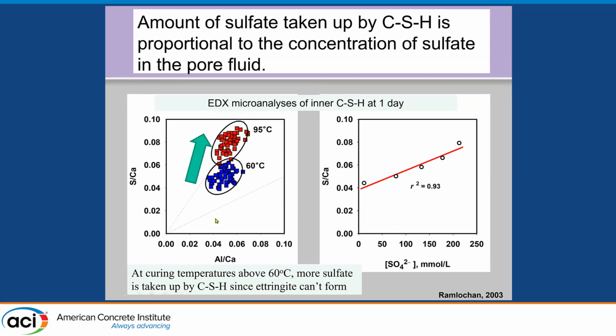And if you look at temperature effects, these ratios of a bunch of EDX points on CSH, what you see here is the sulfur to calcium ratio versus the alumina to calcium ratio. So there's more sulfur in the CSH when it's been cured at these high temperatures, whereas lower sulfur at 60 degrees, which is more representative of what you'd see at the lower temperatures. So there's a big shift in the sulfur that's contained in the CSH itself, and the pore solution increases as well with that higher sulfur in the CSH.